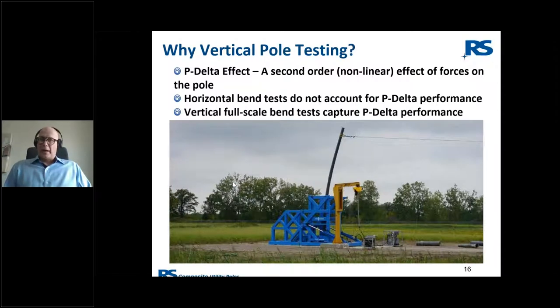So now we get into why vertical testing. So P delta effect, which I just referred to, is a second order or nonlinear effect of forces on the pole, which is to say, if you have a pole and you put a tip load on it and the pole starts to deflect, when the pole moves off its center axis, the weight of the pole will actually add to additional deflection. It's not much, but it is a component. Horizontal bend tests do not account for P delta performance, and it's only in vertical full-scale bend tests where you capture the P delta effect.